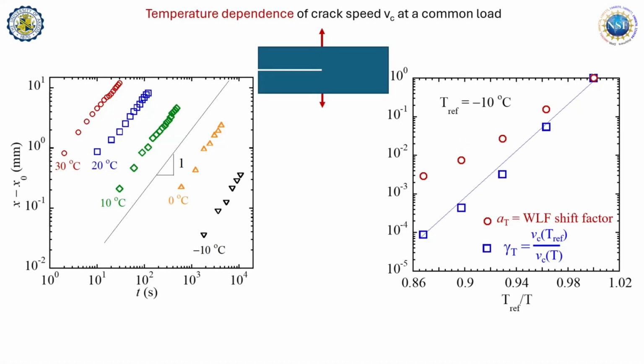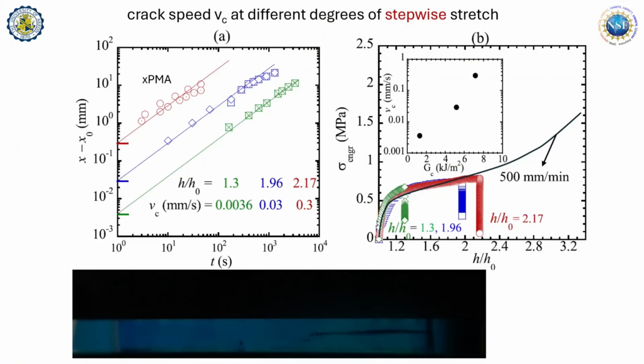Well, we know, but we should show that, right? Because the internal time scale is the bond lifetime, not the polymer relaxation time. Both of which depend on temperature similarly. Lower the temperature, relaxation is much longer. Lower the temperature, your bond is longer lived. So you can also demonstrate that.